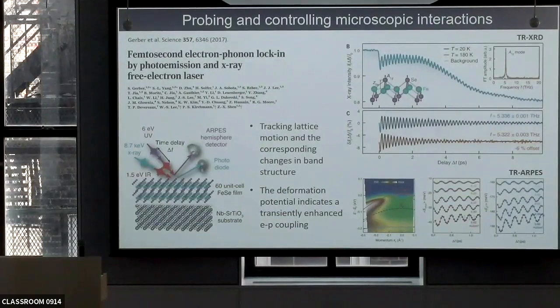But this is a pretty ubiquitous observation, right? In these experiments, usually you pump with some non-discriminating energy, and then all sorts of things happen. The electrons react to the phonons, and one or two phonons emerge coherently. So that's sort of what happens. It has pretty much been shown that unless you go right at resonance, it would always happen, and it's not even so much dependent on the specific photon energy you're using. Correct. So the dependence on photon energy is not so obvious, but that happens by itself, by the system and the interactions in the system.